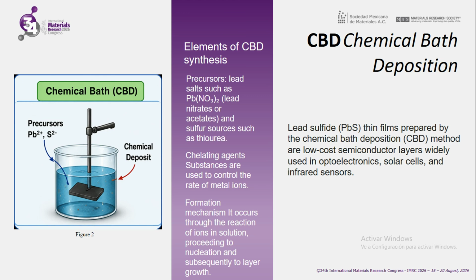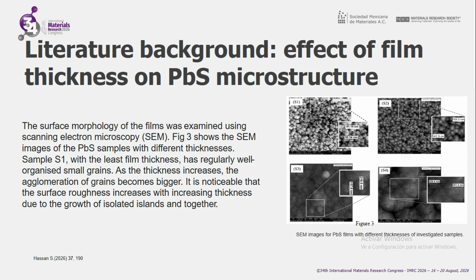Elements of CBD synthesis: precursor lead salts such as lead nitrates or acetates, and a sulfur source such as thiourea. Complexing agent substances are used to control the rate of metal ion formation. The mechanism occurs through the reaction of ions in solution, proceeding to nucleation and subsequently to layer growth. In the literature, there is an effect on film thickness of the PbS microstructure.